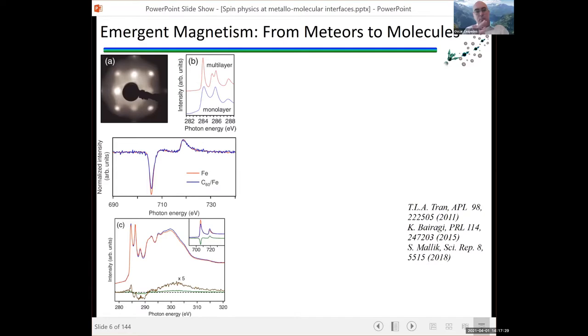And perhaps the first paper, or one of the first papers on this, was from Tran and the groups of De Jong, Van der Wiel, and I think Koopmans as well in Holland. And what they saw is that if you put C60 on top of iron, you change the magnetization of your metal, which you can see in hysteresis loops again, or you can also see here in XMCD in the iron edge, you can see the L2,3 iron edge.